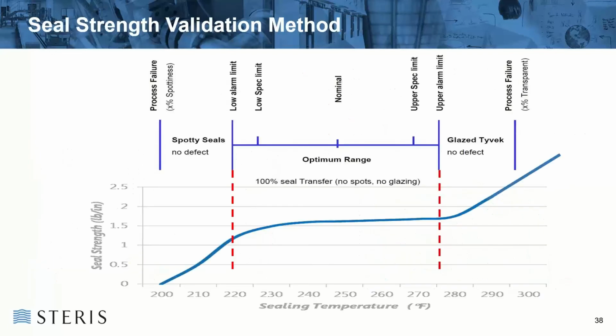Typically, what you're looking for in a seal strength validation at this point is that you're someplace in or around what you defined as your nominal seal strength, or wherever you'd actually started the aging study. If you had gone down, say, 5 or 10 degrees below the nominal seal strength to create your seals, then that's where the seal strength should be at the level it should be, or above, again, depending on which worst case you've chosen. But it shouldn't go below the lower spec limit or the upper spec limit for that seal.